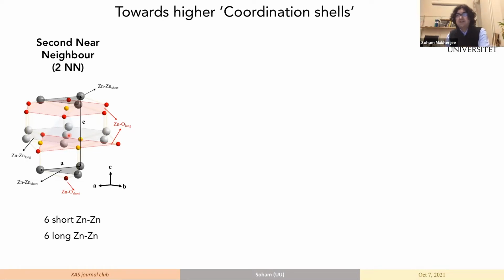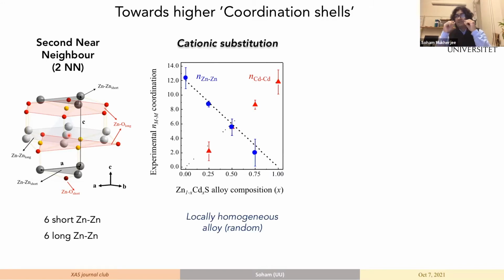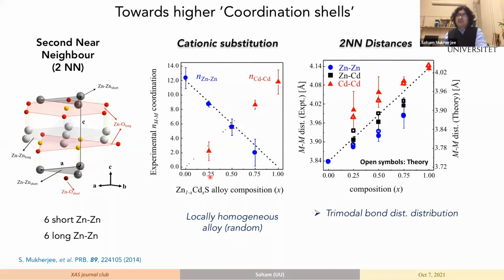Back to the question that Jerry pointed out, the last one, and this is the answer to the question. Locally, when we look at the metal to metal coordination, the number of cadmium around the zinc, we see that both zinc around zinc and cadmium around cadmium go very close to the linear composition that you would expect from the global stoichiometry that we estimated separately, and they match up pretty well. So there is no local heterogeneity in the systems that we are looking at. There is no clustering effect. So the cationic substitution is now confirmed, and we can move over to looking at the number of zinc and cadmium atoms and where they are situated. And here comes the surprise.